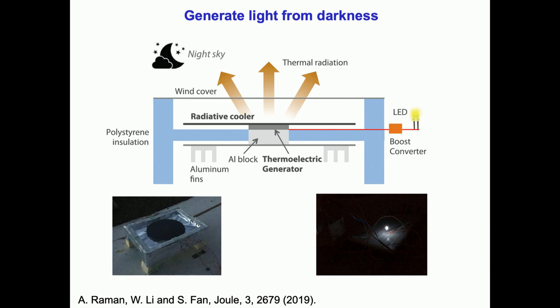So as an initial step towards it, this was an experiment where we take a nighttime radiative cooler, and then we put a thermoelectric generator on the backside to harvest energy from the temperature difference between the ambient and the cooler. And this allows us, experimentally in fact, to generate light from the darkness of the night sky.